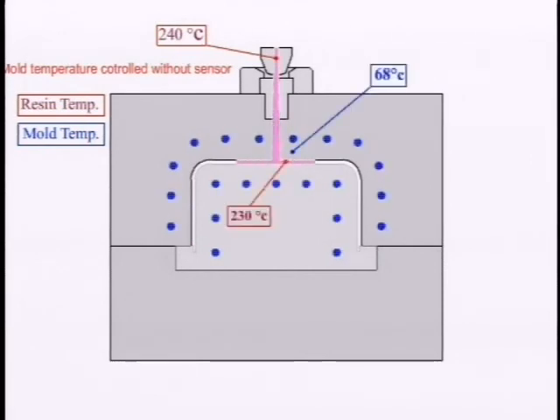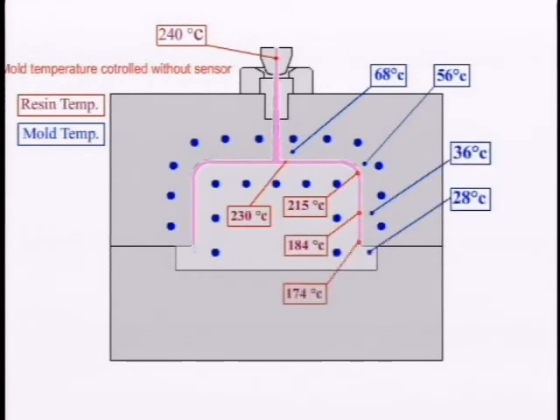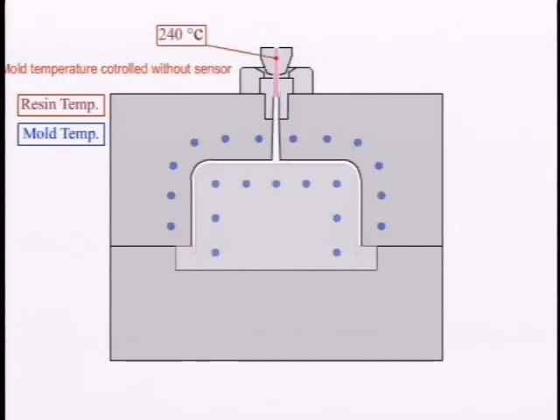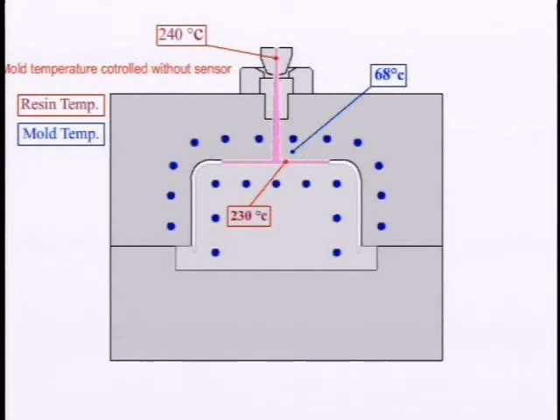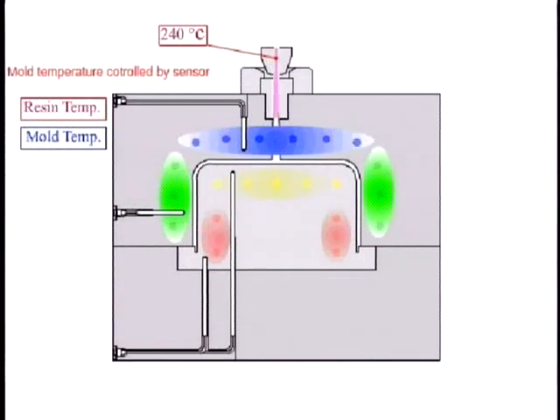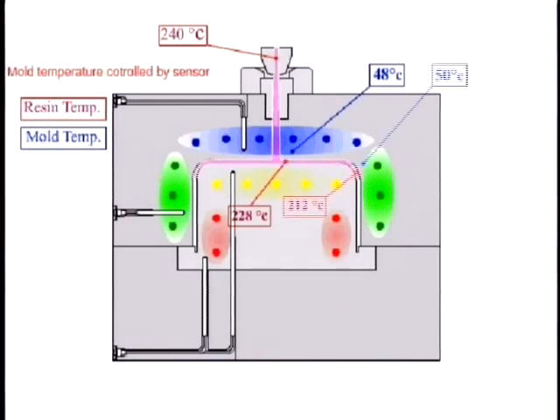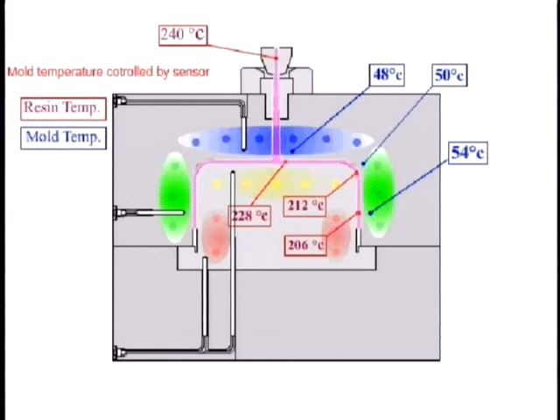In case of the edge of the mold, the mold temperature was 28 degrees, and the resin temperature filled in was 174 degrees. If raising the injection pressure for molding the finished products, we could not help wasting the raw materials. Because of the great difference in the temperature by zone, the solution depends on controlling the change of temperature freely by zone, not controlling only one zone.